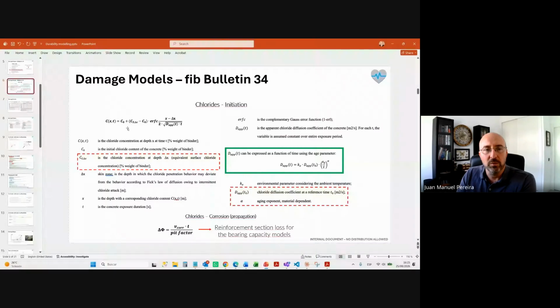But this model is telling us what? It's telling us the concentration, C, of the chlorides at X, the depth, how deep inside of the concrete, at the time T, at any time. So we have the initial concentration, this is an effect of wetting and drying, and this function, which is called the error function complementary. It's a weird name because it's misleading. It's basically the tails of the Gaussian function, you know, the normal bell curve, that gives you how much the ends are, because it's the complement. You can also do the center.